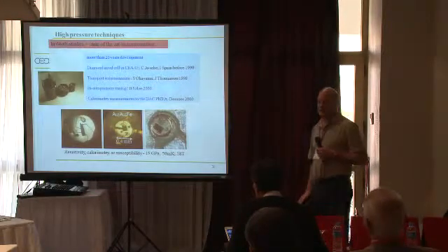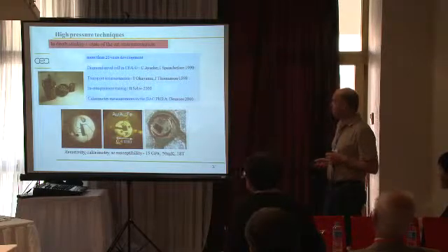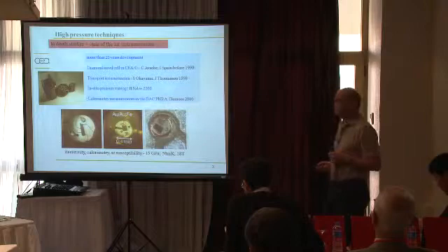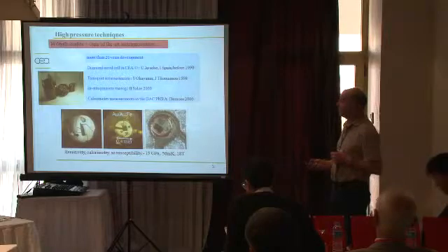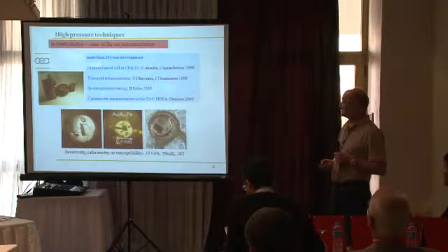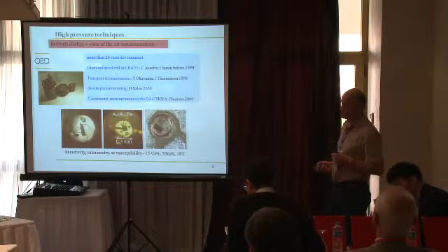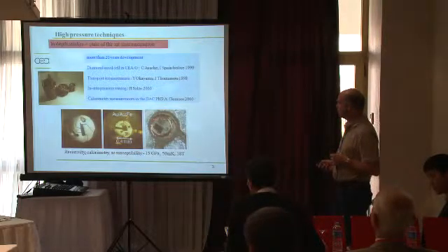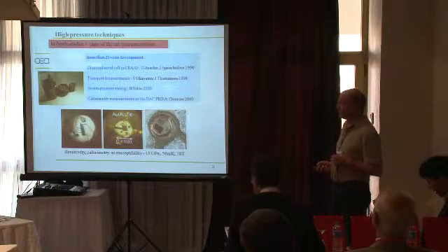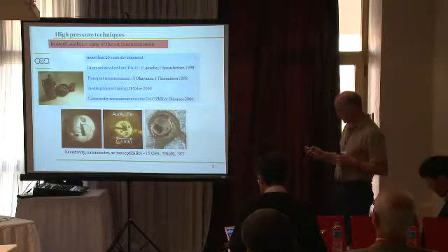Another specificity of the group is that in addition to these physical studies, we've always had a strong effort in instrumentation, and this is particularly true in the field of high pressure, where in the lab it's more than 20 years of development with many, many people involved, which enables us to do what we do today, which is to use the diamond anvil cell to reach very high pressures in good hydrostatic conditions, but above all to be able to introduce wires into the sample chamber so we can make, for example, resistivity measurements, but also by putting a thermocouple on the sample, specific heat measurements, or by introducing a tiny coil into the sample space, AC susceptibility measurements. You see the specificity of the diamond cell is the tiny dimensions of the sample chamber and so of your sample.